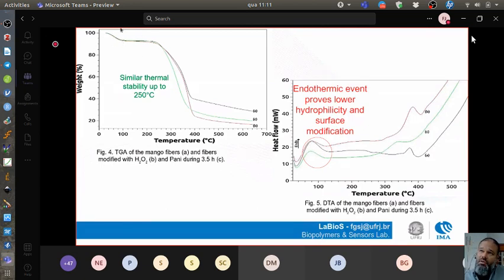Okay, so when we think about this specific range of temperature, we can try to extract more data from the DTA. In the right corner of this picture, we can see these three peaks related with the enthalpy of this loss of water. And it's very interesting because, as you can see, the peak related with the material modified with PANI is the smallest among all of them. So it is proving to us that this surface, after the modification with PANI, is more hydrophobic, proving the surface modification.